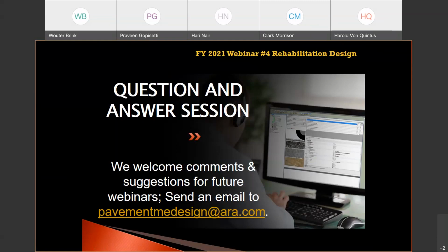The first part of that question, Wouter, repeat that? Sure. Would fractured JPCP be an appropriate choice to model a severely deteriorated underlying concrete pavement? Yes, it could be. Again, it's going to depend on the type of cracks. If this was a jointed plain concrete slab that had multiple mid-slab cracks, there's a limit when you select fractured jointed plain concrete pavement. There's an upper and a lower bound for the crack spacing, and that would be the only limit.